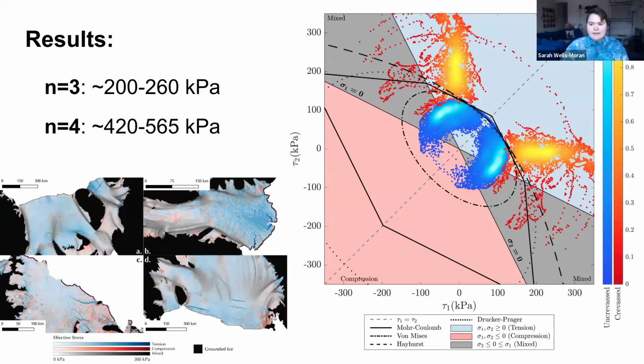So here are our results for tensile stress. If you see here, these blue points are all areas that are not crevassed. The red are all areas that are crevassed. And this color scale tells you the density of points in that area. And then these lines here are all of our best fit yield criteria. You can see there's a decent separation between the areas that are crevassed and the areas that are uncrevassed. And we change the tuning parameters to change the size of the yield criteria and calculate how many points are in versus out of the criteria. Our results for n equals 3 are tensile stresses between 200 and 260 kPa, which is within the range that David Vaughan predicted. And then for n equals 4, we see higher yield stresses of 420 to 565 kPa.